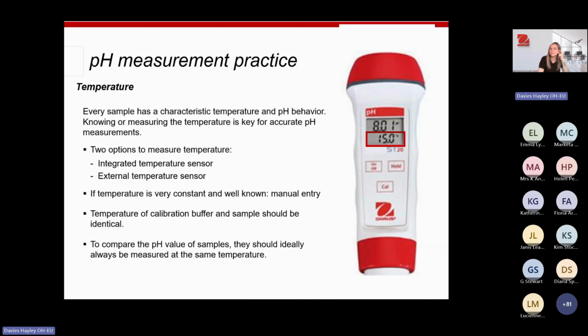Temperature. We did touch briefly on the fact that you do get electrodes that have an integrated temperature sensor. This is because pH is directly affected by temperature, so knowing the temperature of your sample is critical for accurate readings. There's two ways you can do this. You can have an electrode that has an integrated temperature sensor, which would be in the shaft with the measurement and the reference electrode, or you can use an external temperature sensor. If you're using an external temperature sensor and you know the temperature of the sample, you may need to manually enter the temperature on your pH meter.